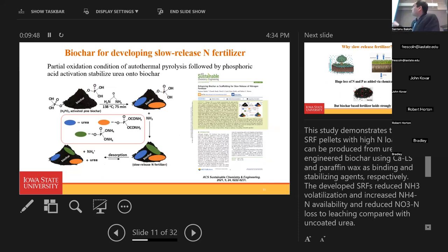In this study, we have shown that with woody biomass biochar, pine biochar, we can do some post-pyrolysis treatment with phosphoric acid, and we can do some urea melting, and we can develop some phosphate phase on the biochar, and that biochar can be used for the urea molten phase on the biochar. And upon desorption, the nitrogen will be available. So we can call it a slow-release nitrogen fertilizer, on the right-hand side.